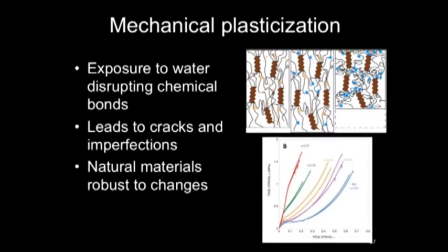Because, as I had said previously, exposure to water disrupts these chemical bonds. This leads in synthetic materials to those cracks and imperfections that lead to quicker failure than if it's dry, whereas natural materials are robust to these changes. As I had said before, this causes an increase in extensibility, but also a lack of loss of strength.